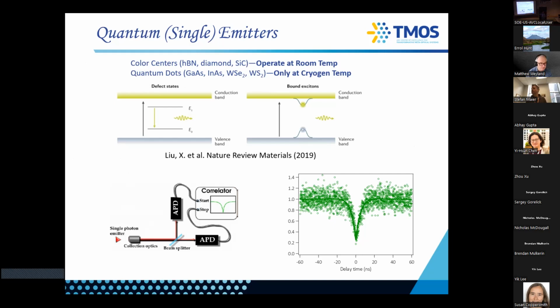And if you go to wide bandgap materials, there are color centers. So they would have a ground and an excited state very deep within your bandgap. So in this type of system, you would need maybe 4 or 5 eV bandgap materials, which makes the research fascinating. It also makes it very comfortable because a first-year student can go to the lab, pick up a diamond, drop it on the floor, pick it up, put it back in the confocal microscope, and everything still works, right? You don't need to operate dilution fridges or cryogenic fridges. Although, again, the technology is evolving, obviously.